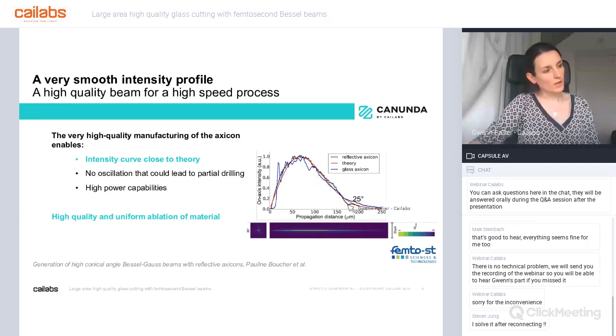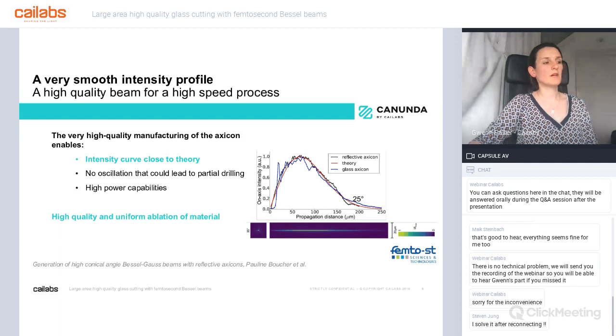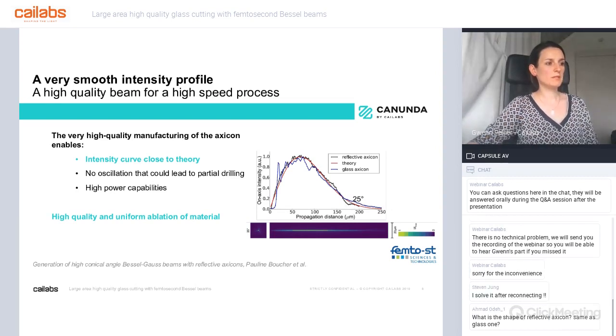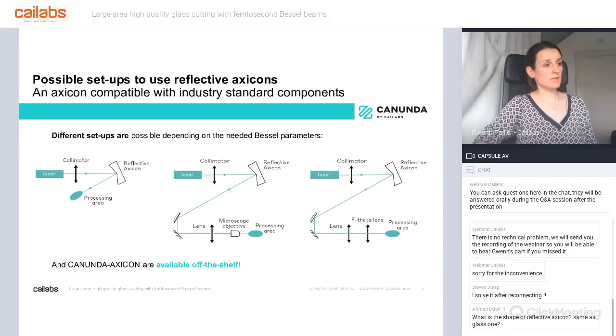I just want to mention that here you have a little difference between the theory and the actual measurement. It's not because of the AXICON, it's because of the laser beam. As most of you probably know, it's pretty classical with femtosecond beams that they have kind of wings at the edge of the Gaussian beam, and those wings create this little difference. So we were pretty happy with the quality of the generated beam. And this cannot be seen with a transmissive AXICON.